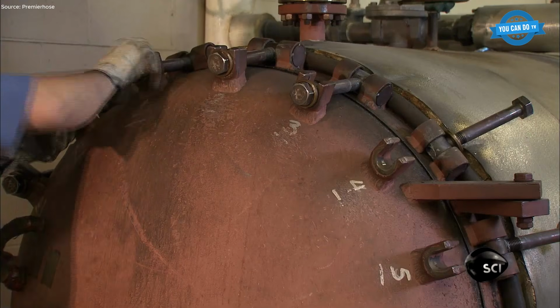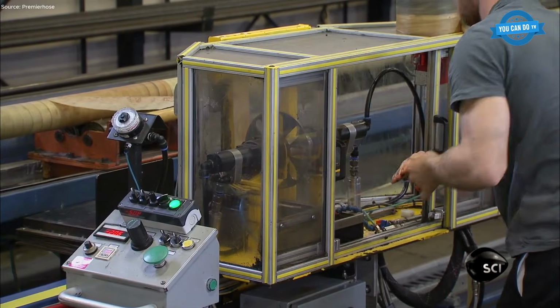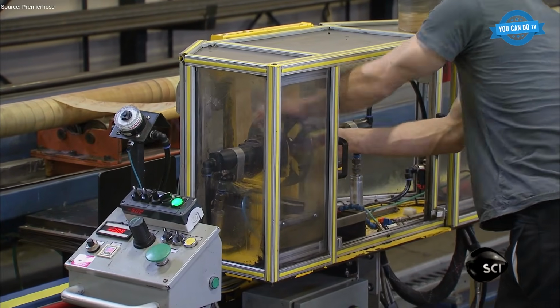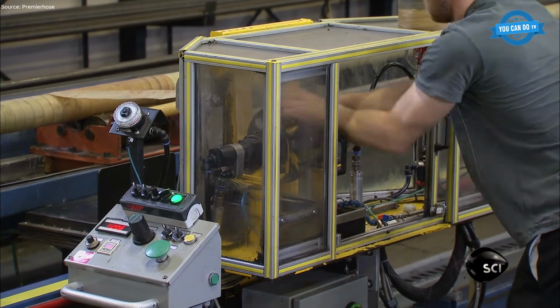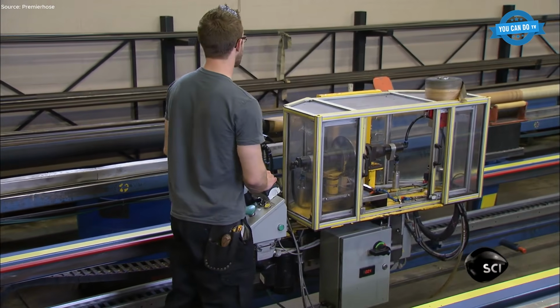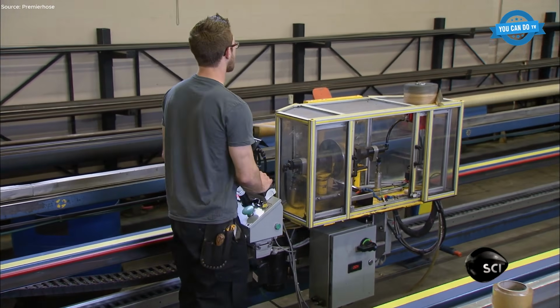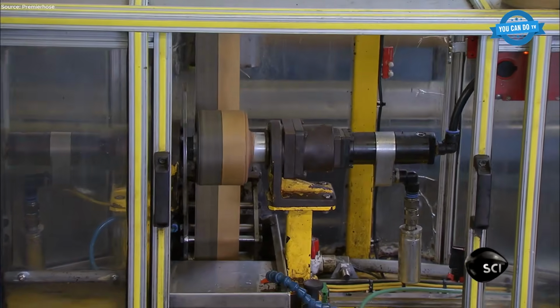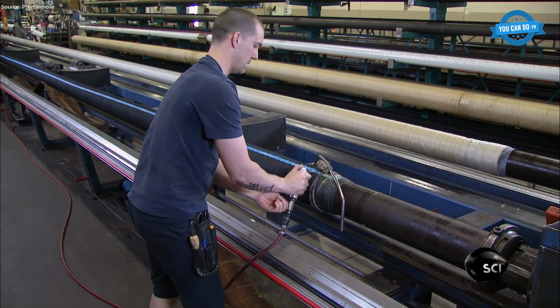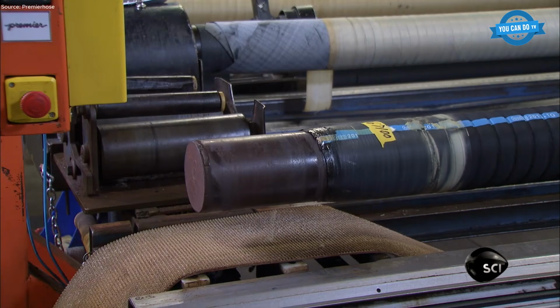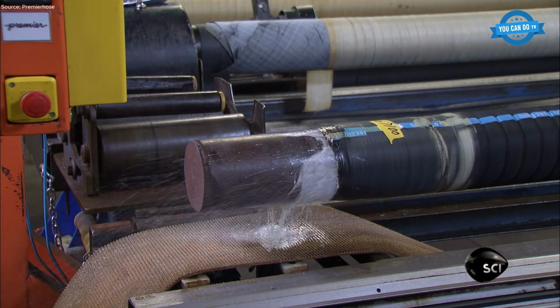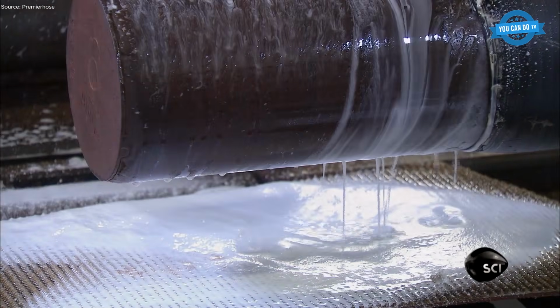The assembled hose undergoes vulcanization inside an autoclave at approximately 150 degrees Celsius. Heat and pressure cure the rubber, permanently bonding all layers into a single elastic structure. After cooling, the hose is removed from the mandrel, trimmed, dimensionally inspected, and prepared for delivery. The result is a highly engineered industrial hose built to perform reliably in demanding environments.